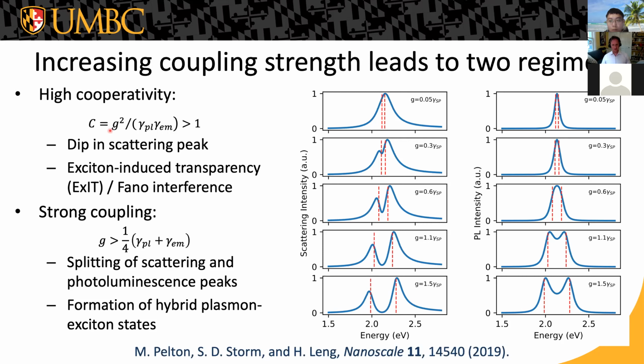We're in the kind of opposite regime here, the bad cavity regime in the plasmonic case, instead of the good cavity regime that's typical of photonic cavities. Okay, so the fact that for the EIT you measure it with scattering, but for the strong coupling you use photoluminescence, I guess that doesn't change the line widths involved and stuff like that. So the induced transparency doesn't show up in photoluminescence.